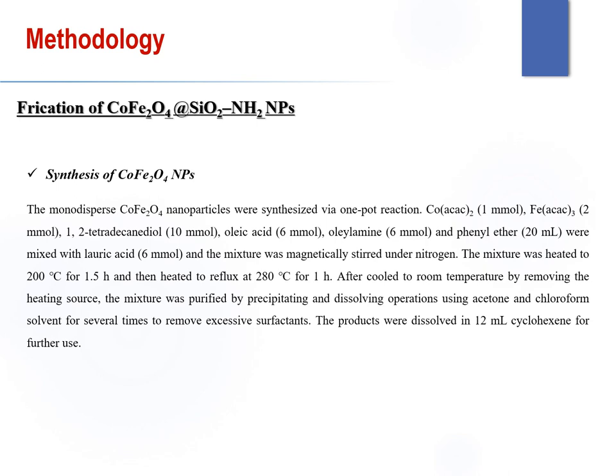The monodisperse CoFe2O4 nanoparticles were achieved via a one-pot reaction. The mixture containing the precursor and surfactant was heated to 200 degrees centigrade for one and a half hours and then heated to reflux at 280 degrees centigrade for another hour.